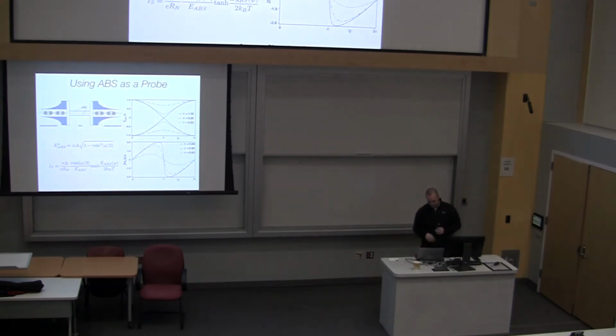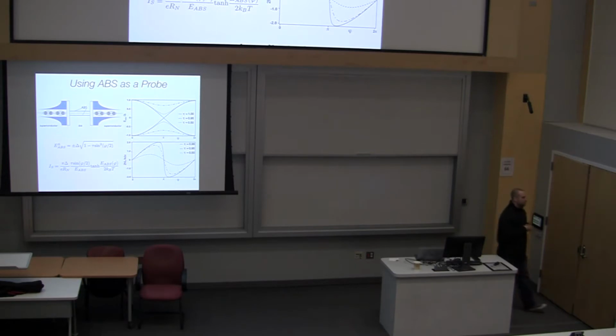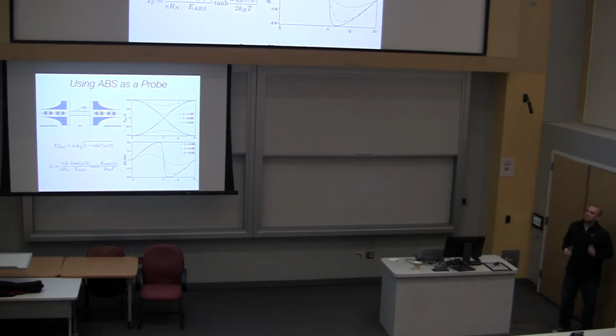And typically, that whole all else stuff going on, bulk conduction, et cetera, doping at the surface, these are the things that dominate transport. So when you do transport measurements, you don't see anything interesting because it's all shunted out by this large bulk contribution or some non-trivial surface state that exists on the surface. Now what we want to do is tease out some of the interesting features that may or may not be on the surface using a Josephson junction. And I'd like to illustrate in these next few slides how we actually do that.